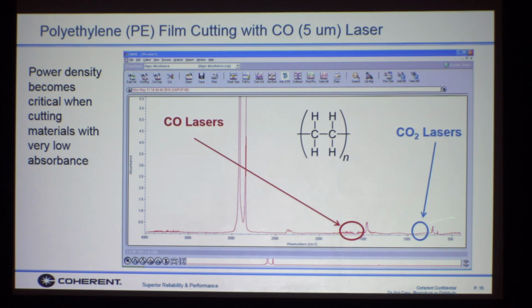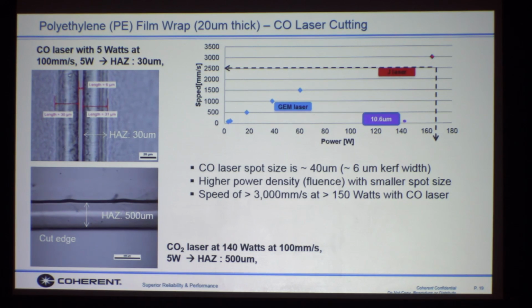CO2 lasers, you can see here, there's a small, tiny background amount of absorption, but not much. The same with the CO laser. But what you can do with the CO laser is you can focus the beam down very tightly, down to 40 microns, and that creates enough fluence to drive this process. It's very difficult to do with CO2 because you can't focus it as tightly. But again, you get 4x the power density or fluence with the CO laser over the CO2 laser, and that